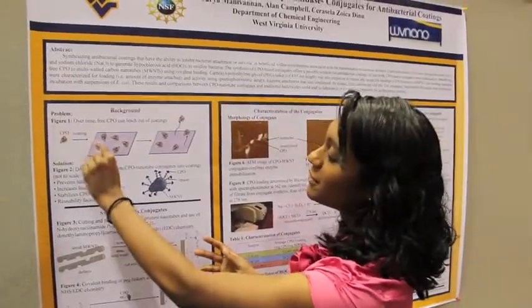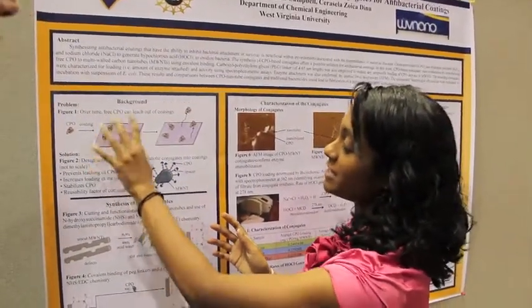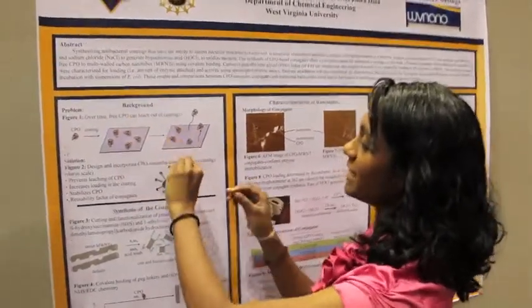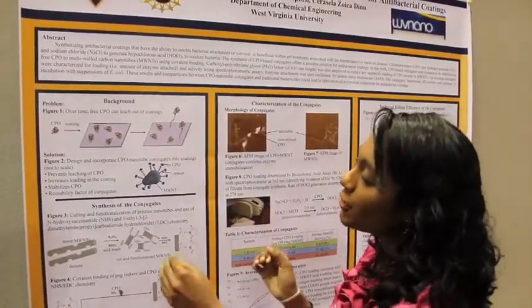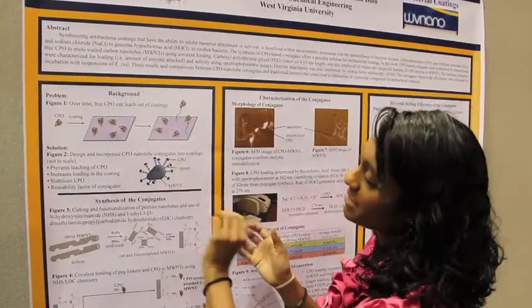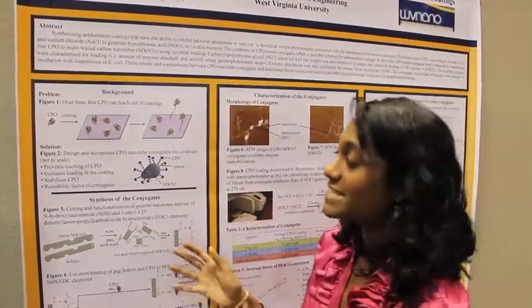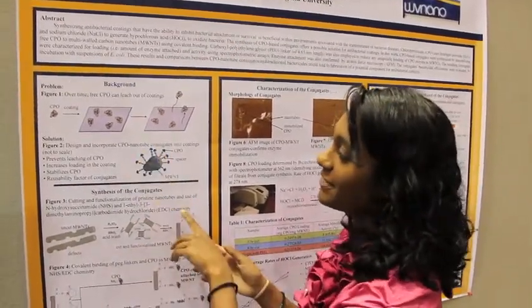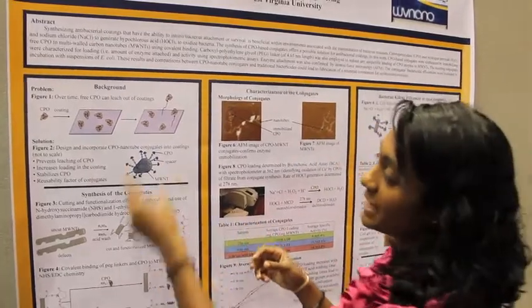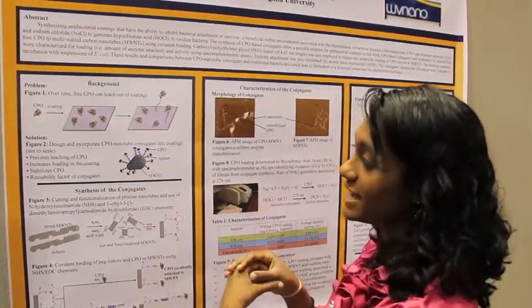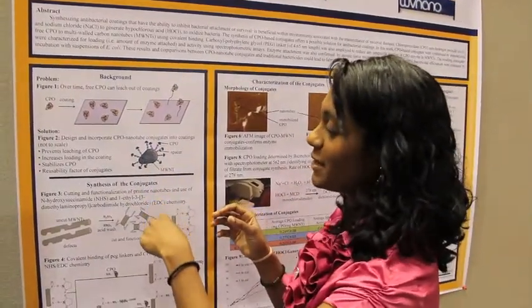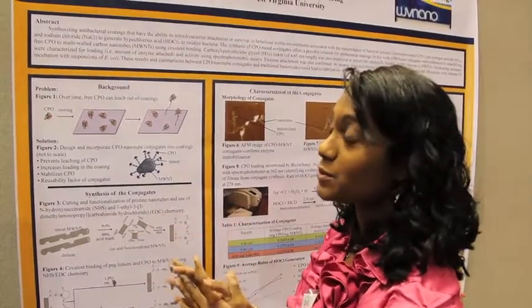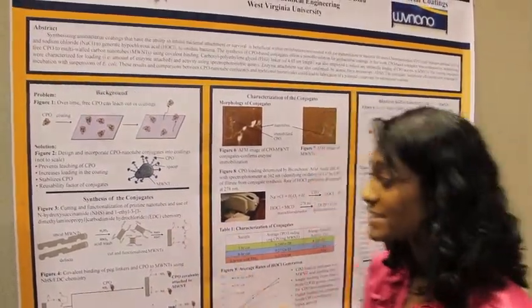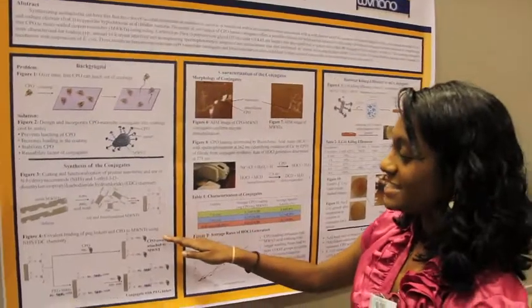And the problem is, whenever you incorporate just free CPO into a coating, it leaches out over time. So the solution is to immobilize them onto nanotubes in order to stabilize them. And this would prevent the leaching and also increase the loading into the coating to increase the surface area. And it would stabilize CPO and add something called a reusability factor, which would be very beneficial as an industrial process.